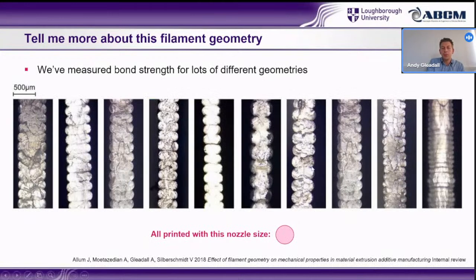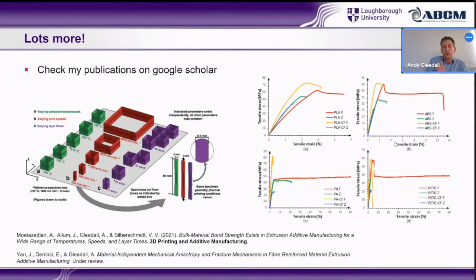And also with the size of these, they're very quick to print, which means we can do lots and lots of different tests and get a really good broad understanding. So these are all different structures that were printed with exactly the same nozzle, material and printers, and we could then calculate the bond strength for all of these to get a really good understanding of whether the findings do translate beyond our immediate study design. So that's an introduction to some of the mechanical testing that we've done.